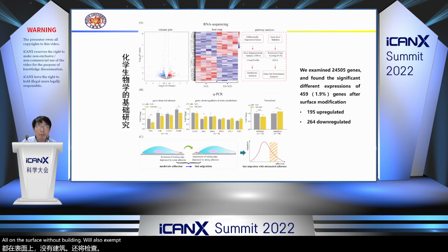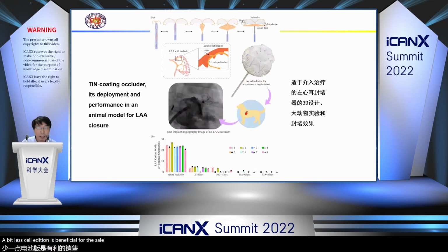We also did some bioinformatics analysis. We examined more than 20,000 genes and found about 2% of genes have been upregulated or downregulated. And we also used qPCR and other techniques to detect the mRNA expression and also the protein expression. So finally, we can realize that after the surface modification, a bit less cell adhesion is beneficial for cell migration. And we also fabricated the 3D structure, and in this way, the device can be put into a large animal by interventional treatment. These data are very valuable about the left atrial appendage ostium.